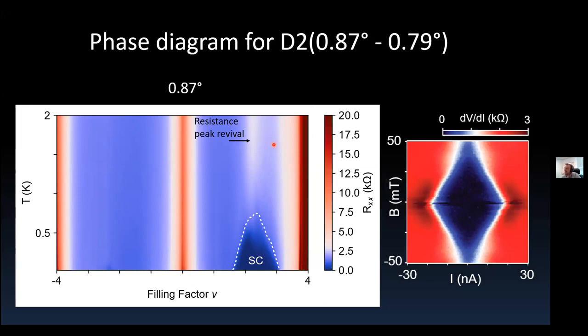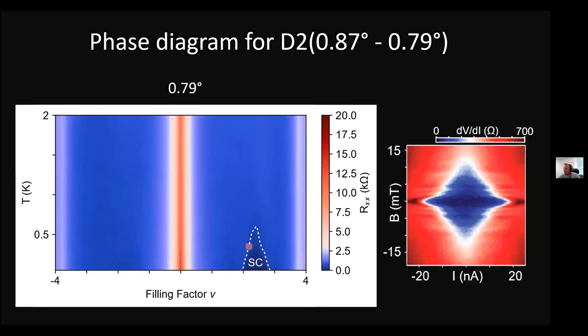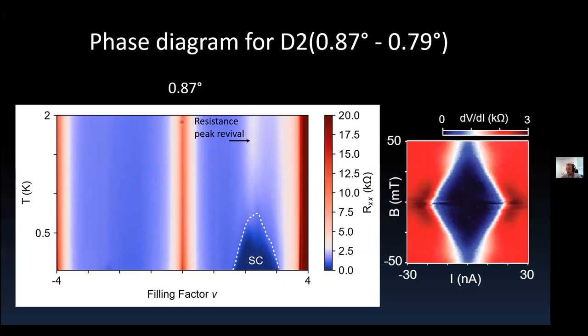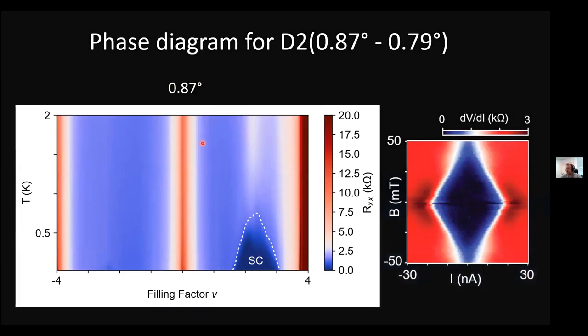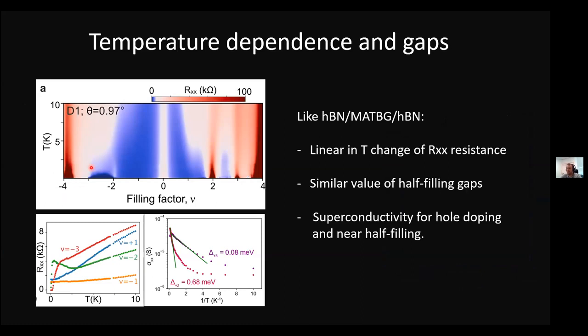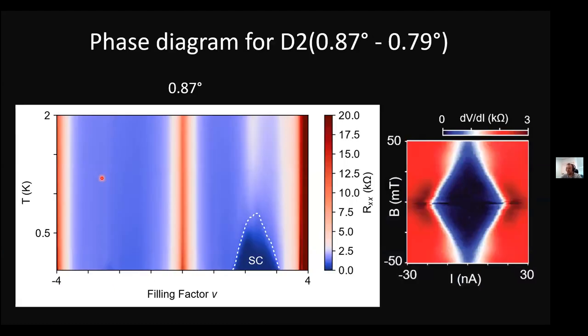So definitely there is some correlation physics present in these samples, and if you go to even lower angles, then even this peak is maybe suppressed, but you still find the superconducting pocket around the same value. Notice that in these lower angle devices, lower than 0.9 degrees, we actually switched from having superconductivity on the hole side to the electron side.